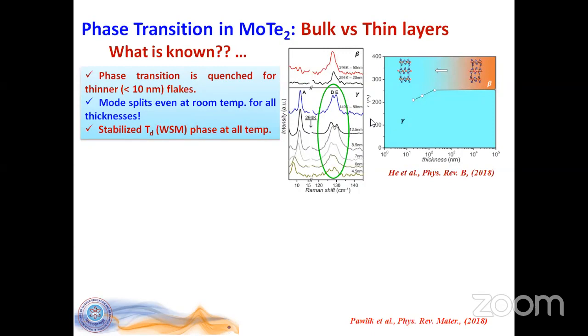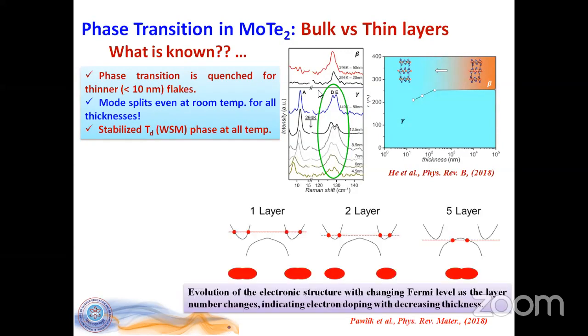Now in the earlier article, if you really see, this particular exfoliation was done in nitrogen atmosphere, and that makes it very clear that in nitrogen atmosphere, the low temperature phase will be favored.